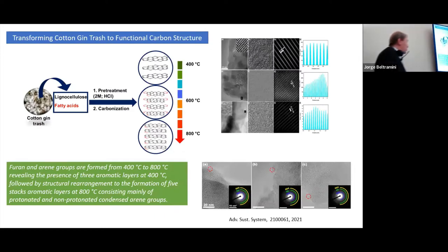But also with the cotton gin trash, what we do is an acid pretreatment and carbonization, and then we create a carbon. We create a particular carbon structure that consists of aromatic layers that are rearranged in a different structure, and then the distance between the aromatic layers gives the carbon the possibility to have activity and functionality. And depending on the treatment that we do to the carbon is what we get.